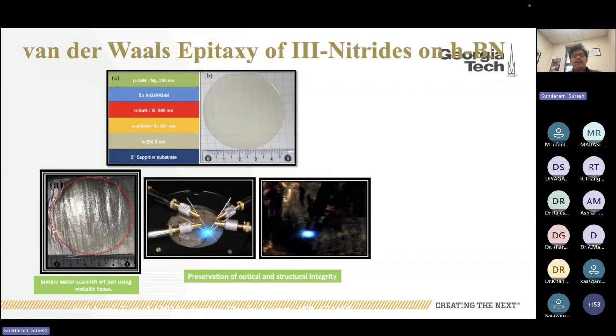So boron nitride is a 2D material, which we are using for separating the substrate and the active layer. So here you are seeing that we are using boron nitride 5 nanometer layers on top of sapphire substrate, which is normally 430 micron thick, and it is a single crystalline substrate. So we are decoupling the top layers, which is less than a micron, from the 430 micron crystalline substrate. But if your 2D layer is thin enough, you can transfer the registry of your substrate through the 2D material into your top layer.